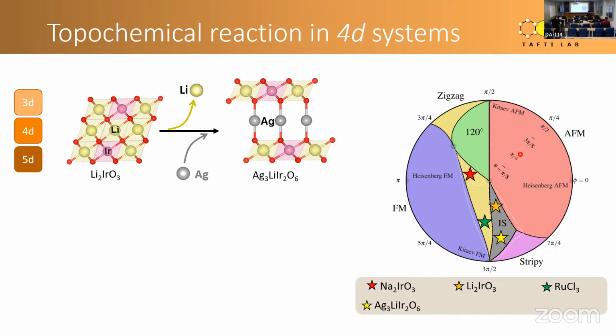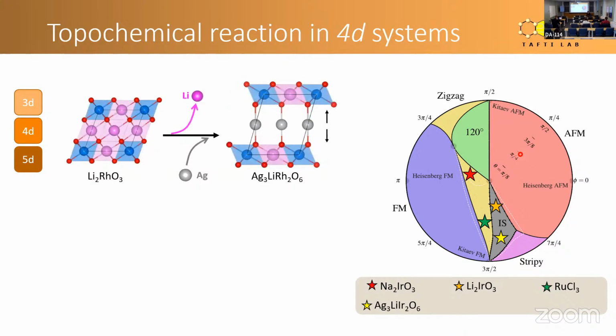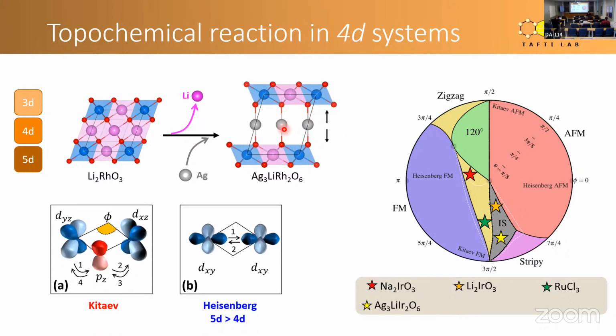But we also extended this research to 4D transition metals. For example, there is a 4D system, lithium rhodate, which can also undergo the same exchange reaction, by removing lithium atoms from between the layers and replacing them with silver. That leads to a new material, silver lithium rhodate. Now, why do we study the 4D transition metals?